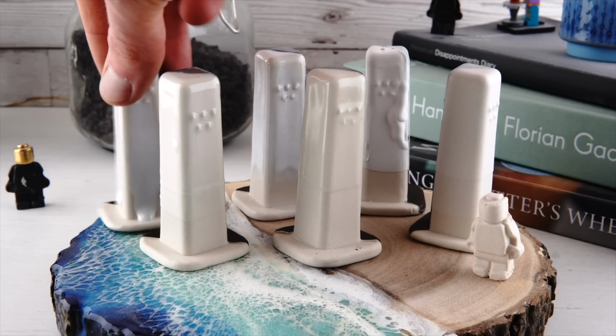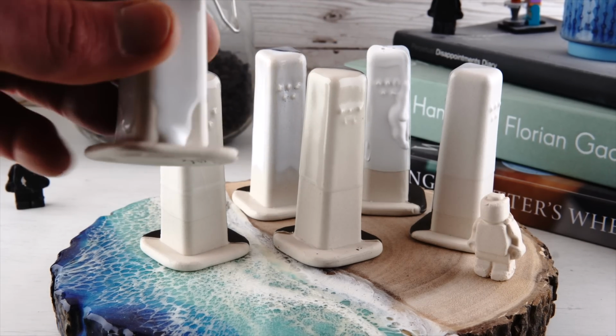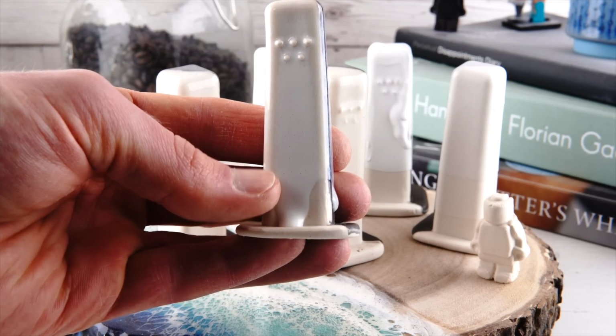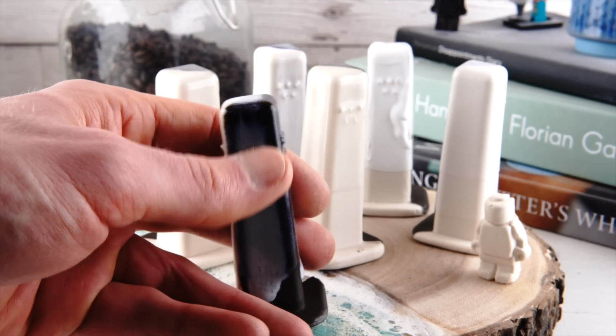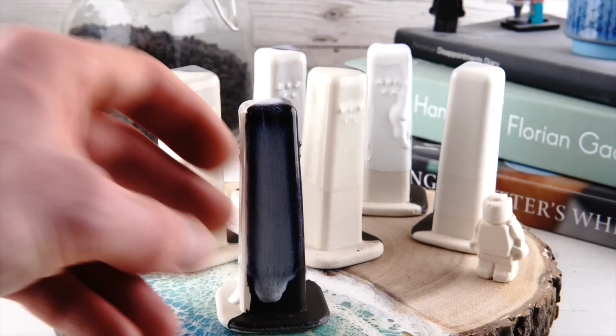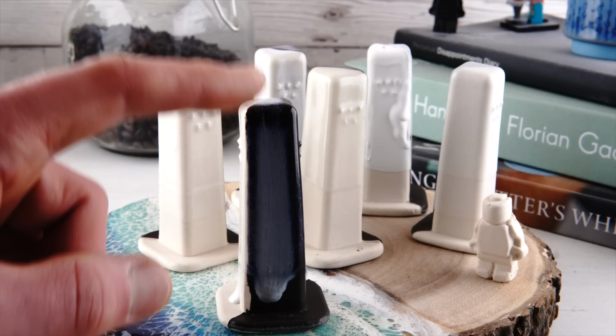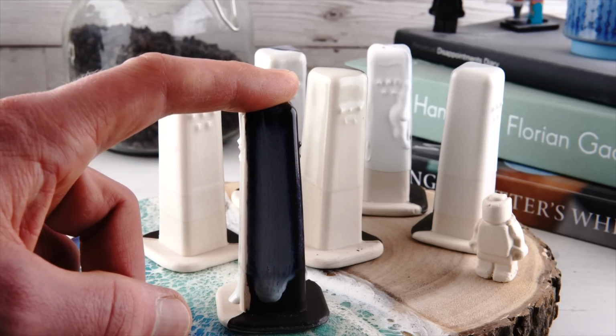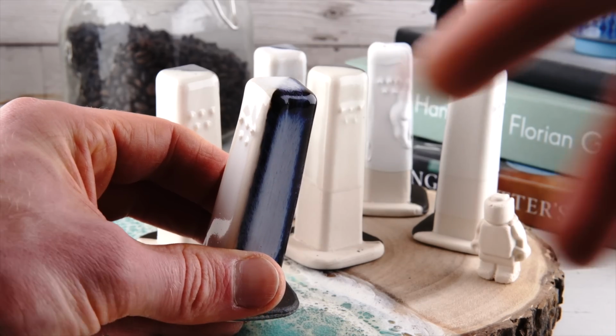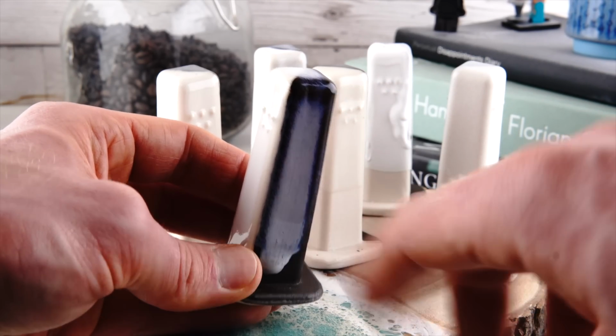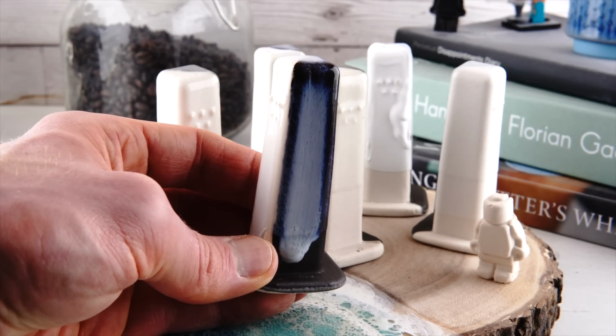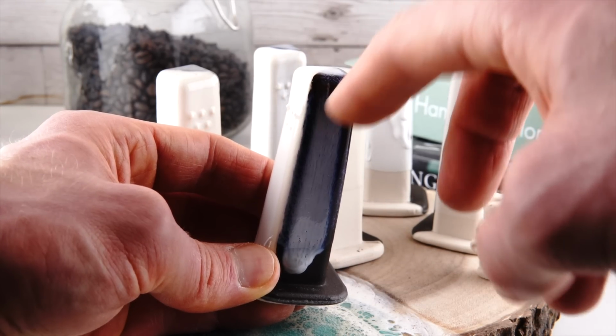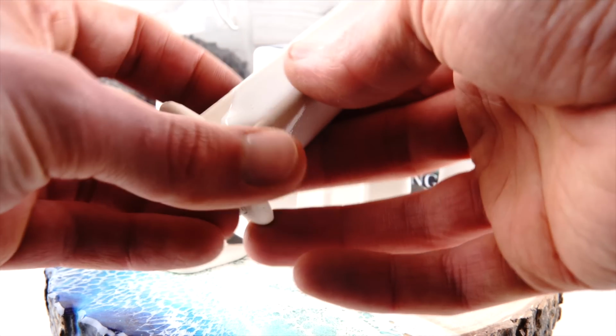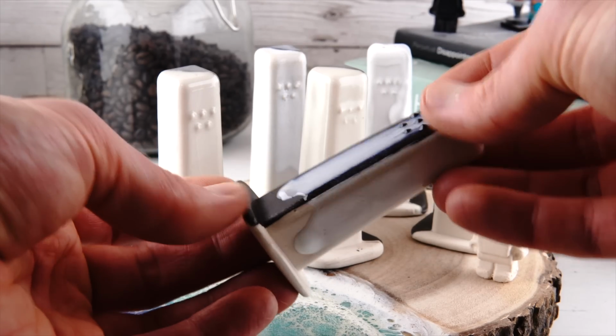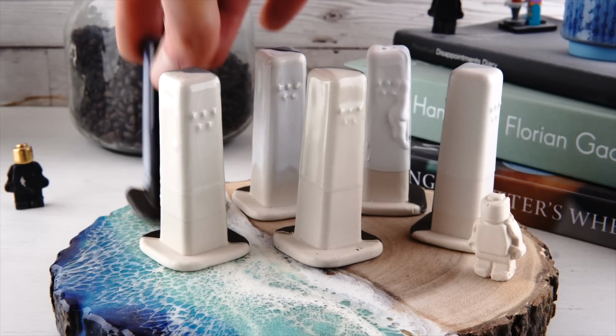So there are 2 that are very overfired, and you can see how much they've run down the test tile, but also how thin they are at the top. They've done some interesting things because there's a lot of boron in there, and boron will behave interestingly at high concentrations. So that isn't a reflection. The glaze has actually gone white because of the amount of boron in it, but it's really thin at the top and it's blistered, and that's a sign of overfiring. And this was the generic recipe with 50% frit in.